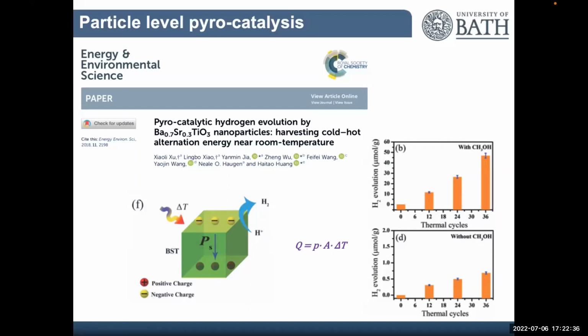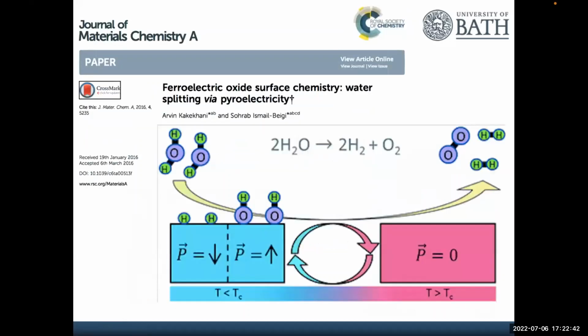I think there's been lots of work that stemmed and originated from this. I saw Haito's work recently that was taking that even further. And there's lots of mechanisms there, as Haito was saying about the band gap. There's also just the straight voltage across the particles. But Arvin Kakekhani does some very nice DFT modeling where he's predicting that the hydrogen is being split over a 180 degree domain where the polarization is up and down, and that splits the water. And then when you heat, this polarization goes, and then the hydrogen and oxygen is evolved. So there's a variety of mechanisms, still a lot of debate, and still a lot of discussion and work to be undertaken there.